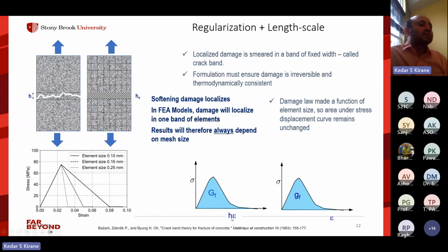And this h, if we can make it equal to the element size, then that means that if we change the element size, we will have to adjust the stress strain law so that the big Gf doesn't change. So this kind of element dependent adjustment of the post peak softening law, this concept is called the crack band theory, and it is often used in conjunction with this continuum damage mechanics approach, this smeared cracking approach. And what it does is basically makes the element size the length scale.